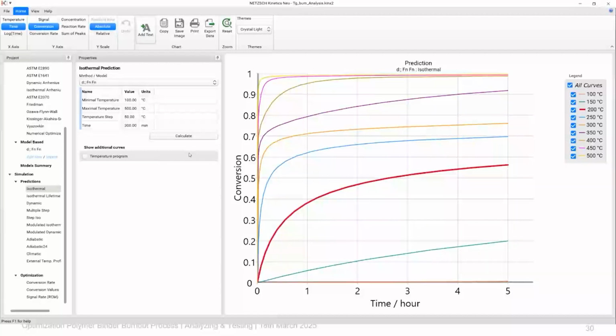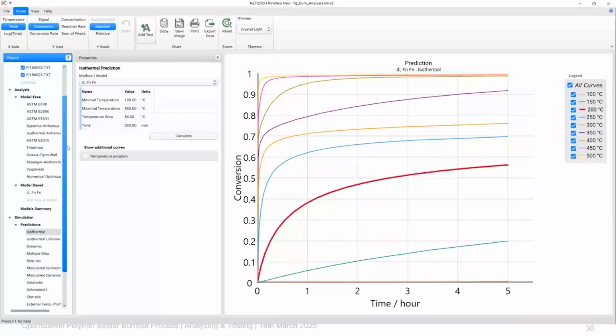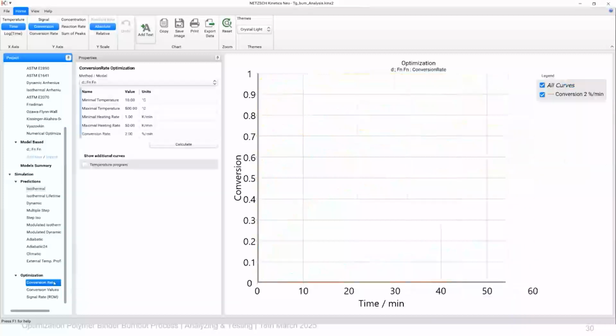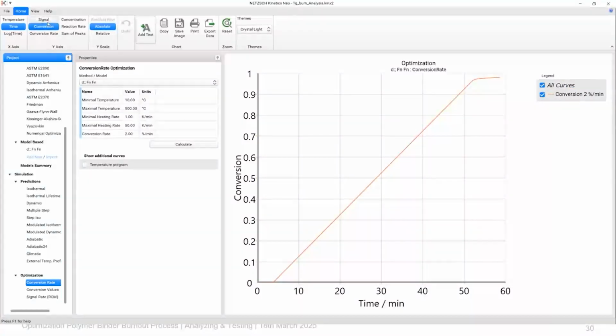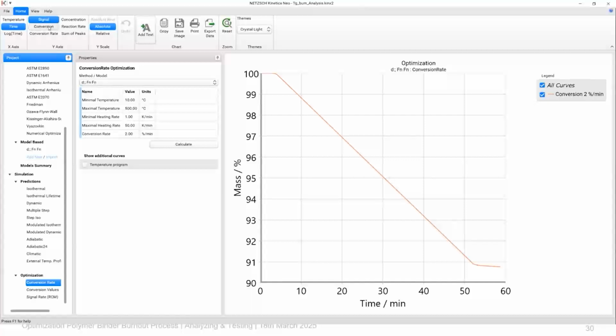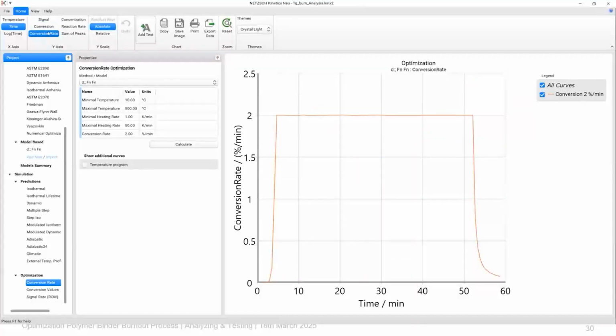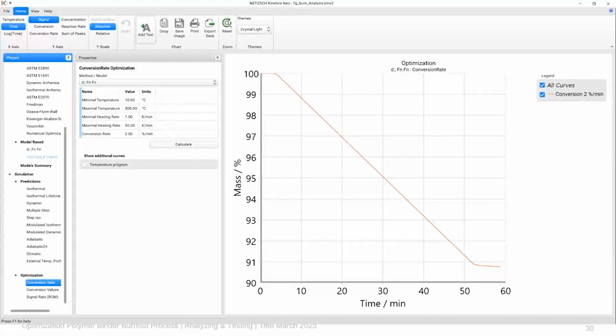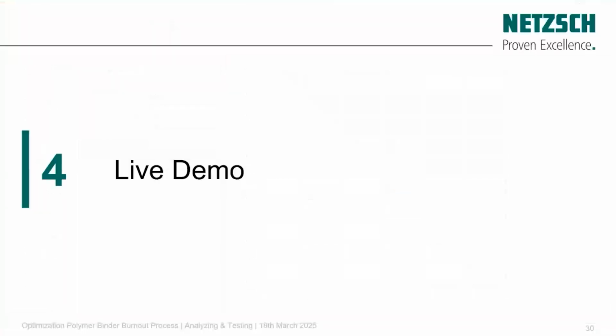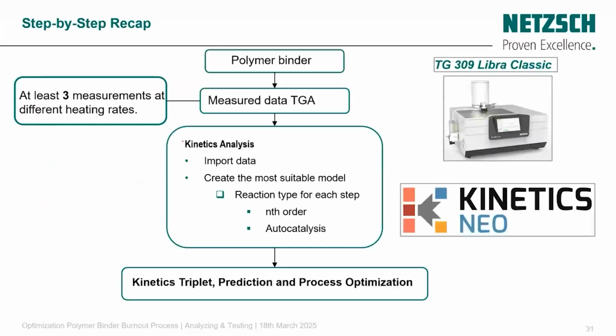So as you can see, with Kinetics Neo software, just by using at least 3 heating rates and in a few clicks, you can optimize your process. And basically here for the conversion we can also get the signal, the conversion, and also the conversion rate. You can see how it's increasing, and we are trying to keep it constant at 2%. Yes, so back to my presentation.